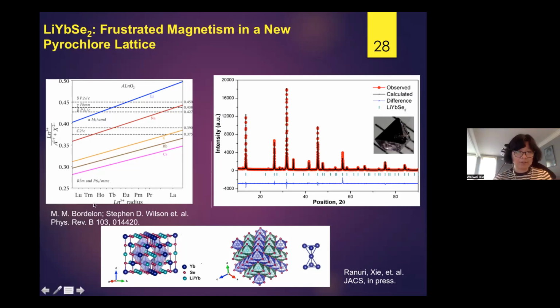Another reference we were reading is the 112 family. This is A, an alkali metal, a lanthanide element, and oxygen. They found there are a lot of different structures in the system. If we change from lithium to sodium, potassium, rubidium, cesium, the structure makes a big change. That indicates this system is very sensitive to chemical pressure: you change the compound larger or smaller, and the structure changes. Based on this, recently people work a lot on sodium ytterbium selenide 2, which is in a perfect regular triangular lattice in the rhombohedral structure. So what I was thinking is, how about we work on the lithium one first?